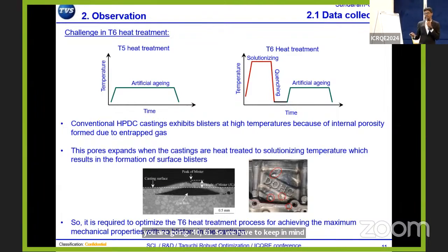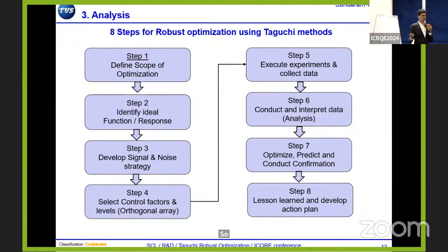You could see this kind of defect will come when we go for T6 heat treatment. So we have to keep in mind that while doing this experiment, we should end up with higher mechanical properties with no blisters in the casting. So we have taken the 8 steps of robust optimization using the Taguchi method.